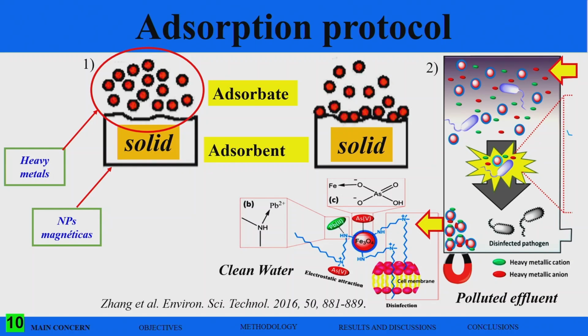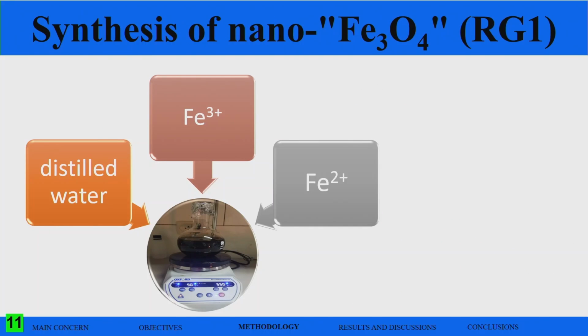And we see the interaction across time. We determine the equilibrium time under certain conditions. And of course, we can take advantage of the specific surface area, the zeta potential, the active sites on the surface, and many other parameters that can influence the adsorption process, right? And we can also be very selective to adsorb arsenic, lead, cadmium, and other heavy metals from water. So I will pass now to the synthesis of the nanoparticles.